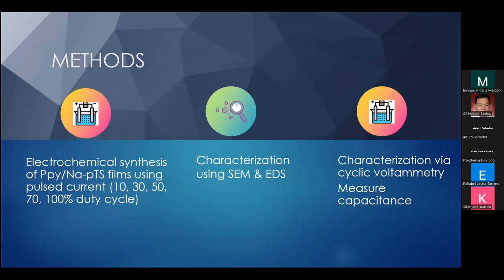In this study, we made our films via electrochemical deposition in an aqueous solution containing 0.10 molar of pyrrole monomer and 0.12 molar of sodium para-toluenesulfonate. The sodium para-toluenesulfonate acts as our electrolyte, to make our solution conductive, as well as our dopant.